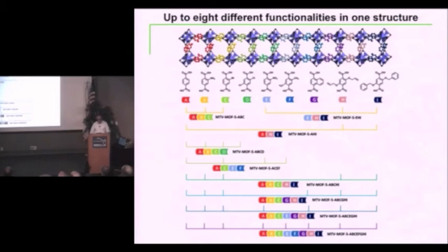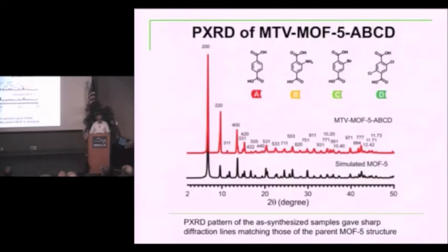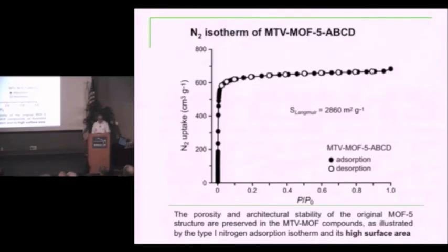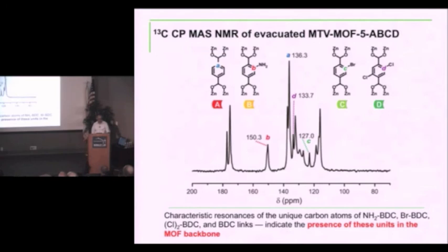And we know a lot about them. We know what they are. First of all, we know we have an ordered backbone, but we know that we have disordered functionalities. The functionalities are covalently linked in the ortho position, but we cannot decipher what is next to what. We know that the access to these functionalities through porosity is possible. We know the ratio of the building units through carbon-13 NMR. And we also know how to vary the ratios of various functionalities.